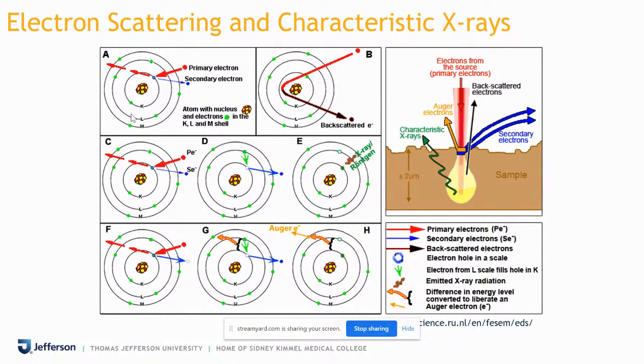and if you incident an electron beam on the surface of these nanoparticles, what will happen is your primary electron will hit and knock out one of the electrons from these K, L, M, N shells. The example shown here shows that it knocks out one of the electrons from the K shell, which is shown as a secondary electron. So this is one thing that can happen when you hit an electron beam on an atom. The other thing that can happen is the electron just gets deflected back and doesn't hit any of these electrons. These are called backscattered electrons.